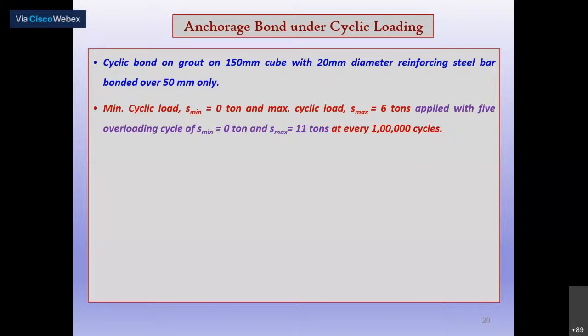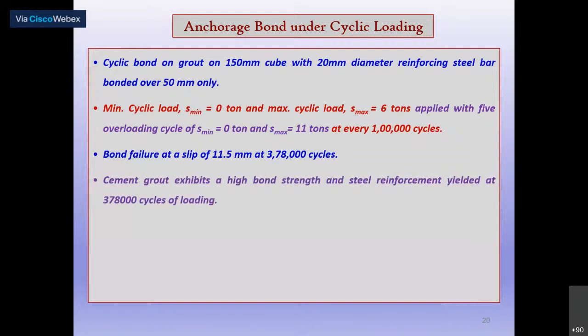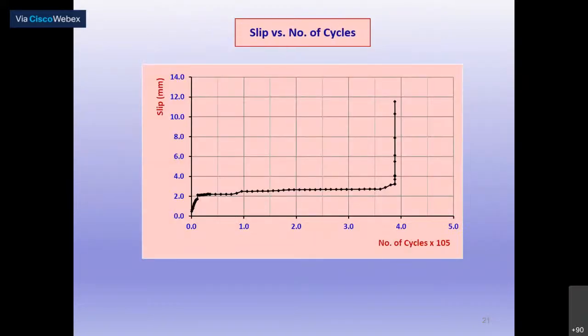When you design the bridge for maximum load and minimum load, say for 50 years, it will work fine. But when the load on the bridge deck exceeds whatever maximum stress you prescribe, the bond stress increases. It is a kind of accidental load. After a number of cycles of loading, maybe after a few years, if you encounter an exceeding load, like an accidental load, then the bond gets deteriorated. That study we did, and we found that instead of 50 years, it failed at about 4 lakh cycles. Due to the accidental loads, the bond failure occurred, and the cement grout failed. This is characterized by the slip versus the number of cycles performed in the laboratory.